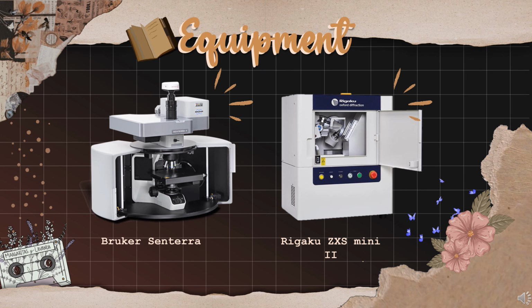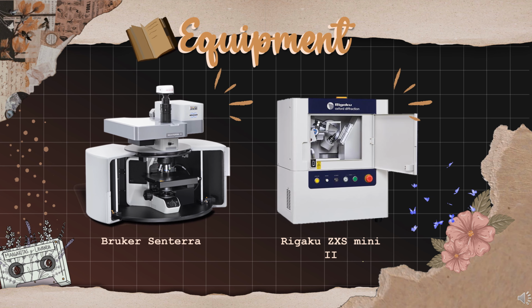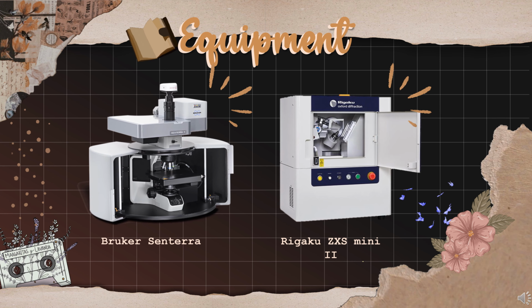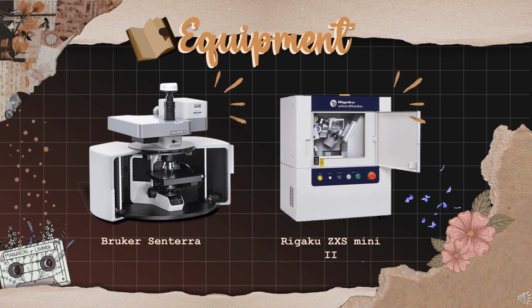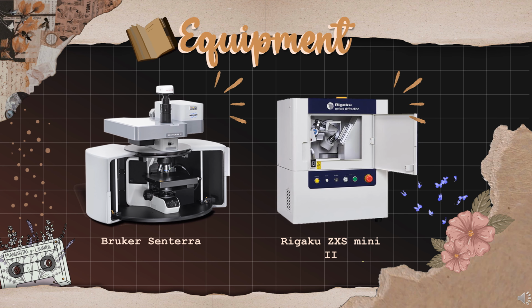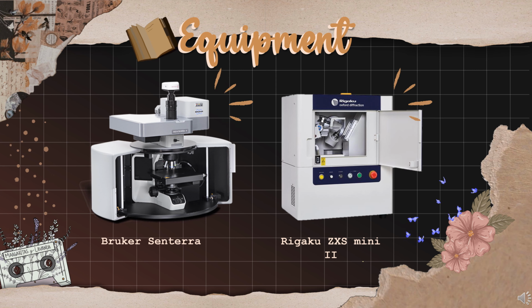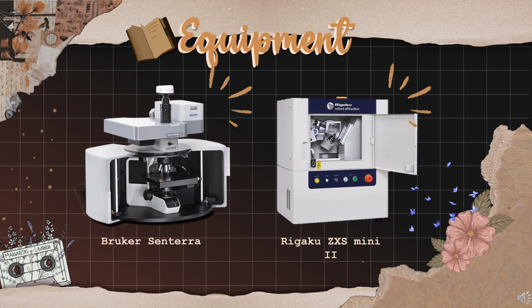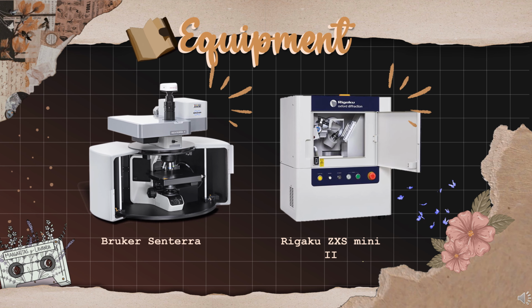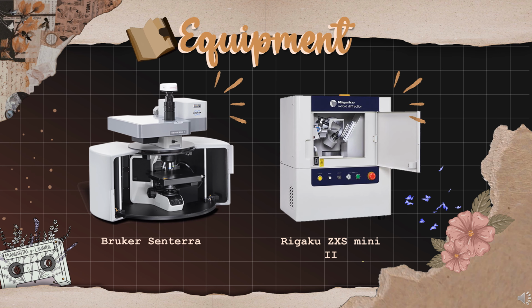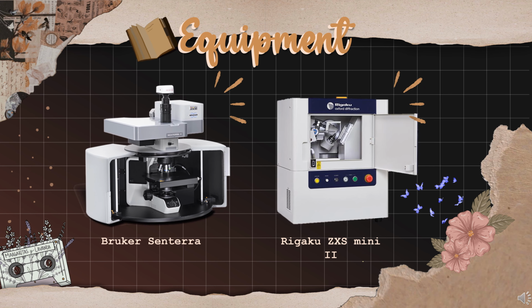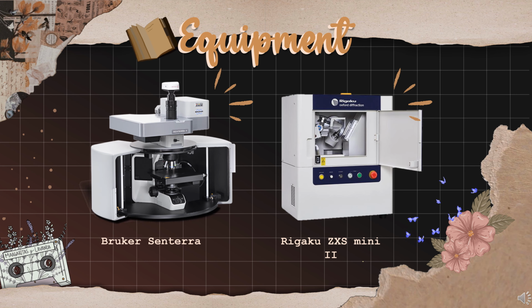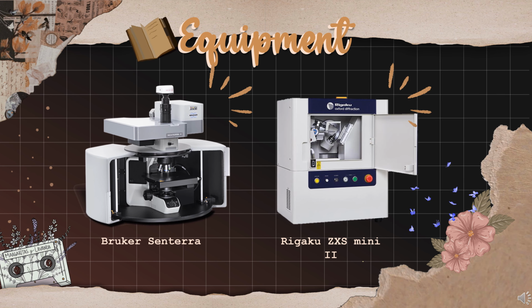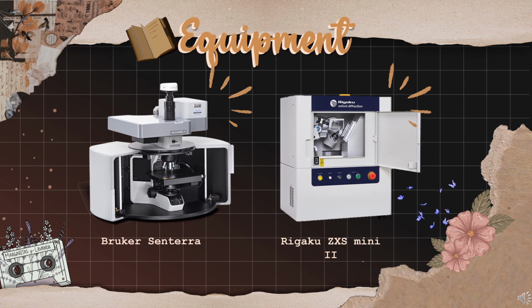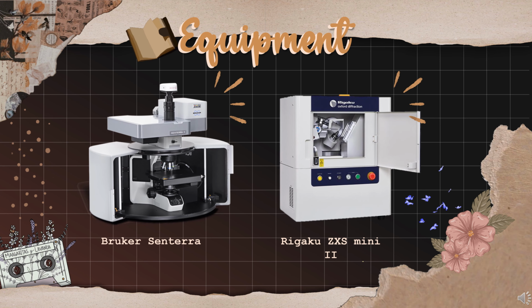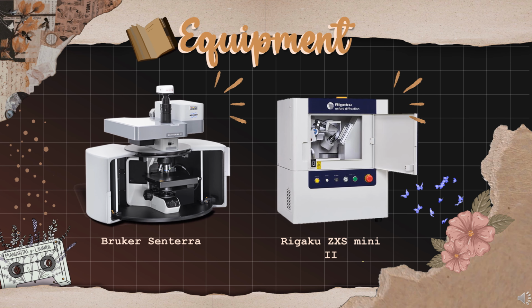Raman spectra were acquired using a Bruker Senterra monograting spectrometer equipped with a charge-coupled device, or CCD, detection system. The X-ray diffraction patterns were obtained using the Bragg-Brentano geometry on a Rigaku powder diffractometer, with samples being diluted with KBr pellets.